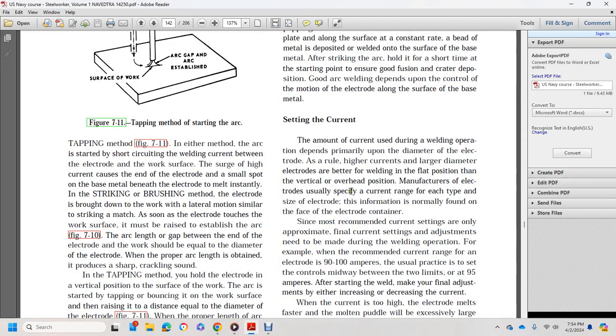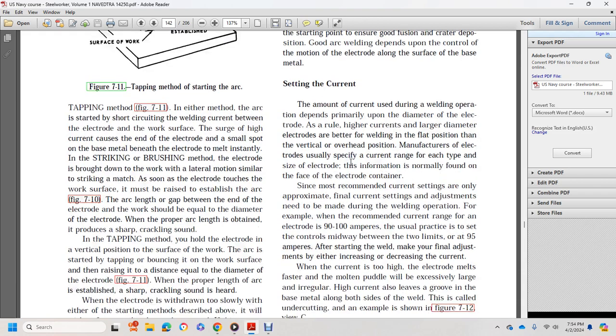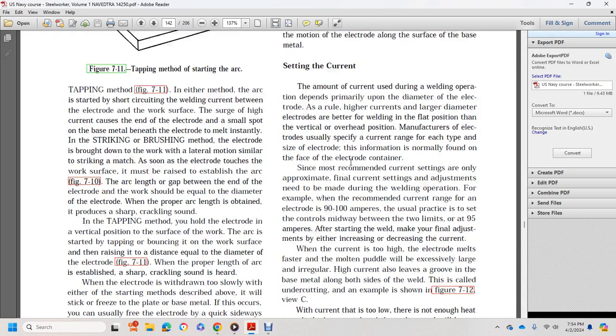The amount of current set during the welding operation depends primarily upon the diameter of the electrode. As a rule, higher current and larger diameter electrodes are better for welding in the flat position than in the vertical or overhead position. Manufacturers usually specify the current range for each size of electrode, and the information is normally found on the face of the electrode container. These are recommended current settings; the final current adjustment is made during the welding operation. For example, if the recommended current range for an electrode is 90 to 100 amps, the usual practice is to set the controls midway between the two limits, at 95 amps, and after starting the weld, make the final adjustment by increasing the current.